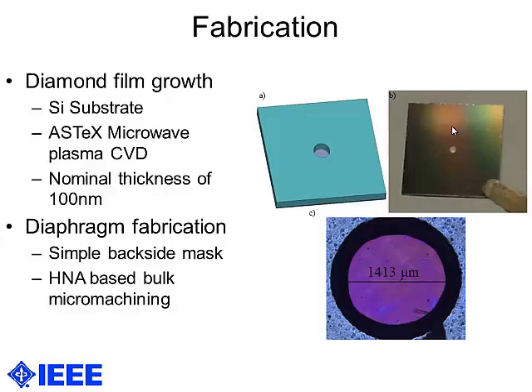The diaphragm fabrication consists of a simple backside masking and an etch for the bulk micromachining. The resultant membrane is circular and in this example, has a diameter of approximately 1.4 millimeters. This gives us an aspect ratio of diameter to thickness of approximately 15,000.